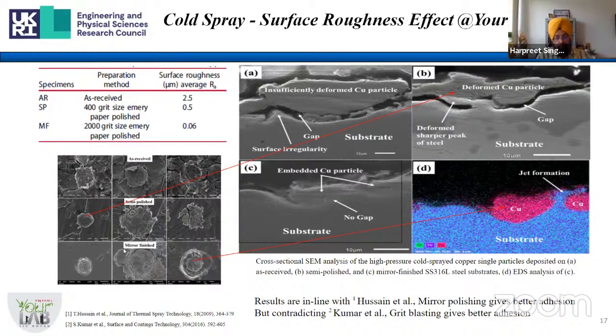In that whole project, one of our students, Surinder, did this wonderful work. The major challenge which we were facing was in terms of adhesion. So we investigated the role of the surface roughness of the substrate on the adherence of our coatings. He used different conditions of substrate in terms of surface roughness. We have mirror finish, semi-polished, and as received. These are some of the roughness values in terms of Ra. Then we deposited these powders.